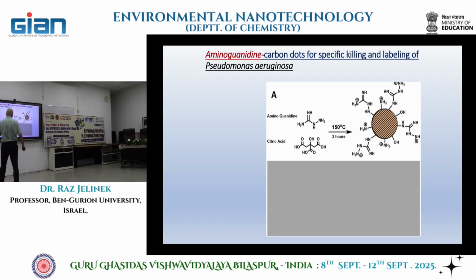We made carbon dots from two carbon sources. One of them was citric acid, what we find in lemon. Very cheap, very easy. And then we took another small molecule called aminoguanidine.